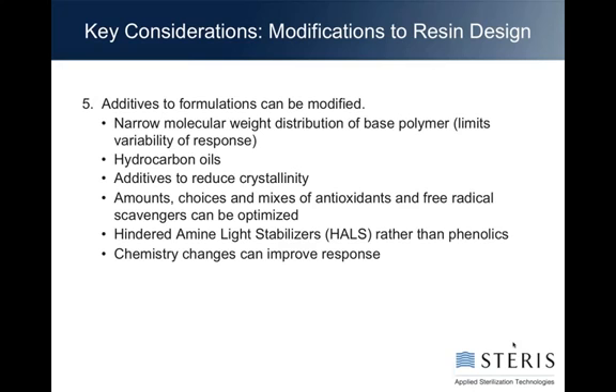Another good one is particularly the stabilizer, the most common stabilizer being the phenolics, which we already know make yellow. There are some that are called hindered amine light stabilizers. Those generally cause less yellowing than the phenolics. So sometimes it can be as simple as getting a homopolymer that isn't stabilized with a phenolic, but stabilized with another additive that doesn't go yellow when it's irradiated. That's why you will see, even though I tell you to look particularly carefully when anything says homopolymer, you will be able to find things labeled homopolymer that are also considered gamma stable. And that's because they're taking into account some of this yellowing.